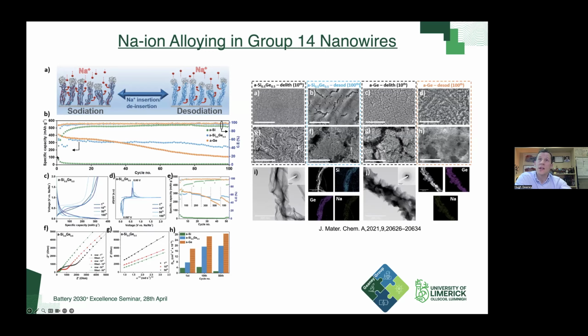And then when we try to cycle the amorphous silicon here, you'll see that we got essentially negligible capacities. So we have no reversibility in the sodium and silicon scenario. We wanted to try and understand that a little bit. Looking at the 50-50 composition at the macro scale, this was the most stable one. What you'll see is that the anode morphology overall is far less pulverized than in the case of the pure germanium. So in this 50-50 scenario, essentially the material hasn't been as impacted by the cycling.